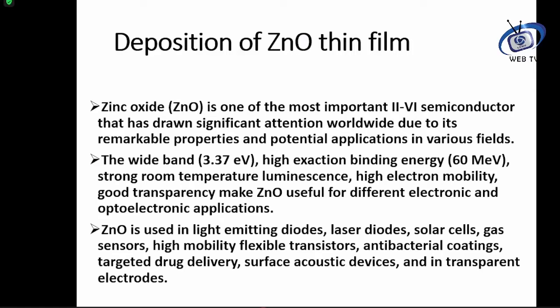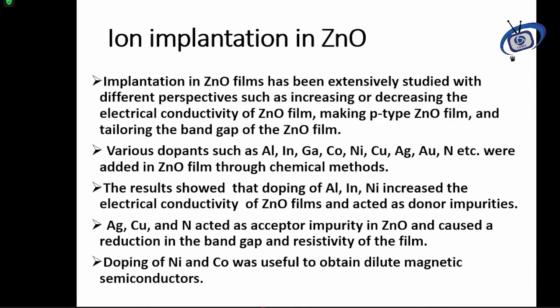Zinc oxide is an important semiconductor. It has a wide band gap of about 3.37 electron volts and a binding energy of 60 milli electron volts. So we deposited the zinc oxide film, and after deposition we implanted ions.